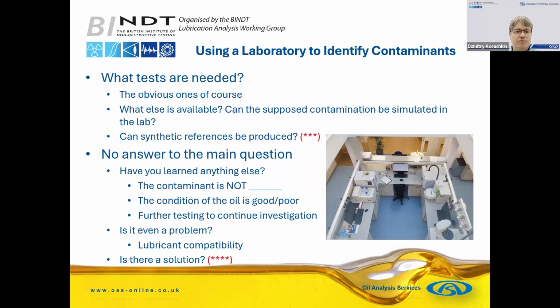So, as I said, if a lubricant is being added in and is deemed the contaminant, in the initial instance where you don't know whether it is going to cause any problems, you could perform a lubricant compatibility study and then determine, yes, actually they are compatible, they are fine to use interchangeably, or we may prefer to stick to one, but if there is a disruption in supply, we're able to use this other lubricant, and it's not a problem. We don't have to immediately drain oil, lose hundreds of liters of oil, and then refill it with a proper lubricant once it's back, because the lubricant that we have is actually acceptable.